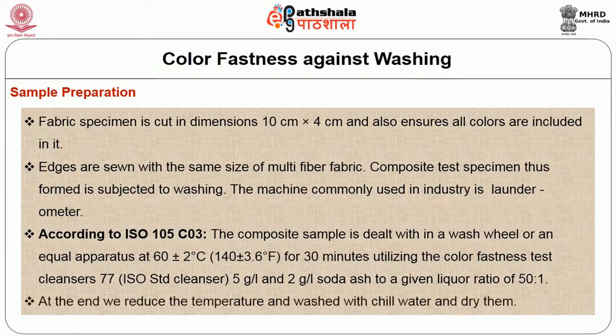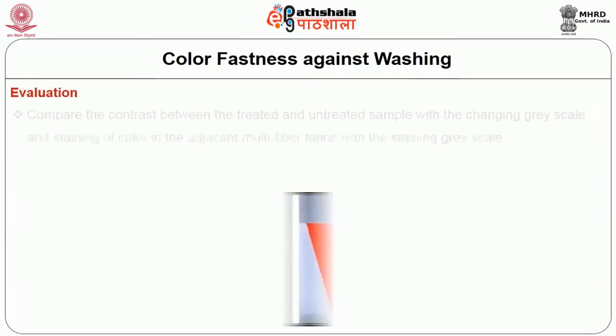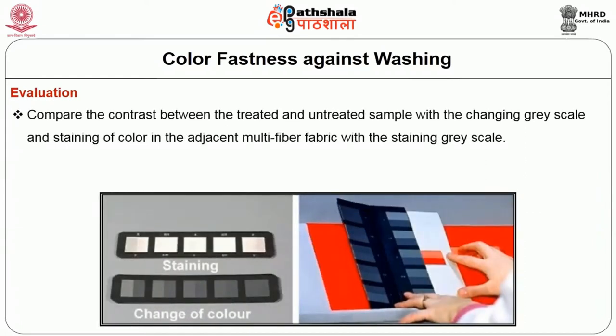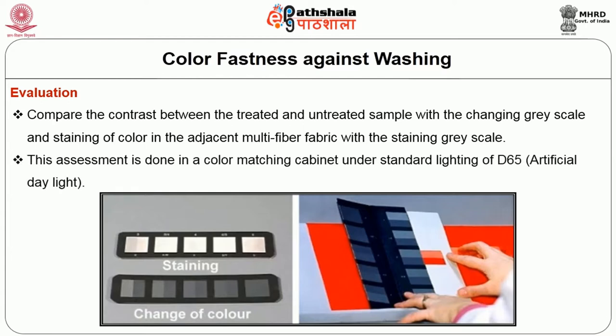At the end, we reduce the temperature and subsequently the woven fabric is washed with chilled water and then dried. Evaluation: compare the contrast between the treated and untreated sample with the changing grayscale and staining of color in the adjacent multi-fiber fabric with the staining grayscale prescribed by ISO. This assessment is done in a color matching cabinet under standard lighting of D65, usually artificial daylight.